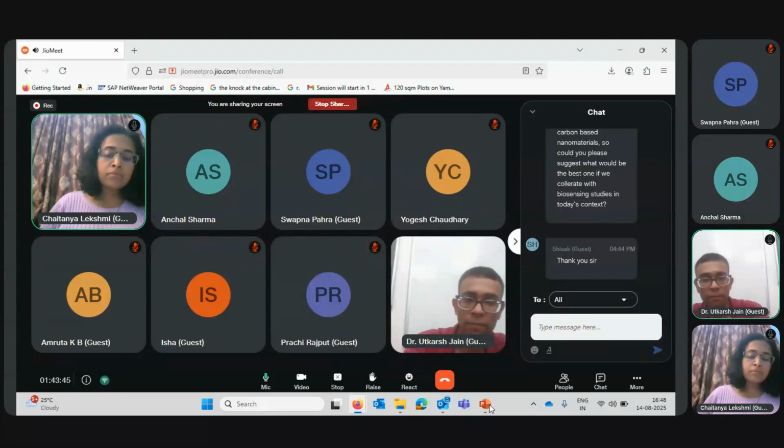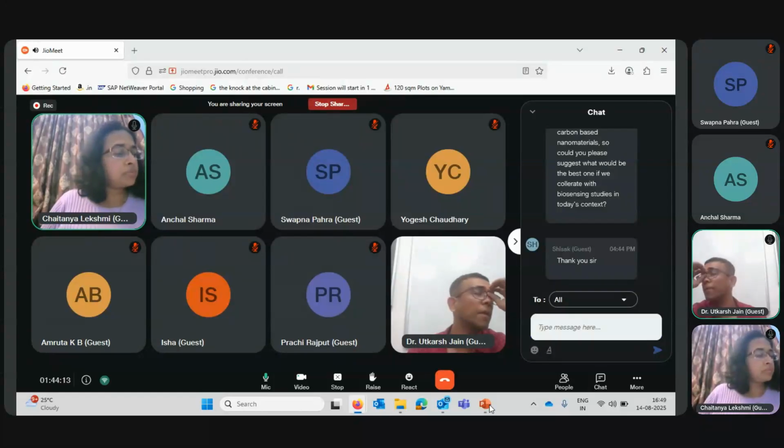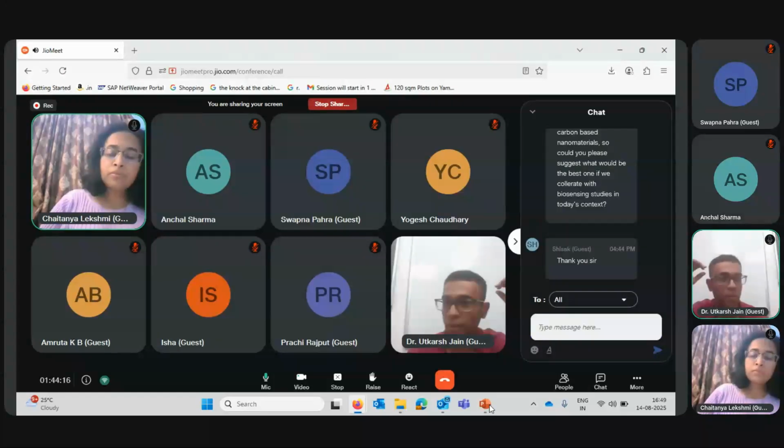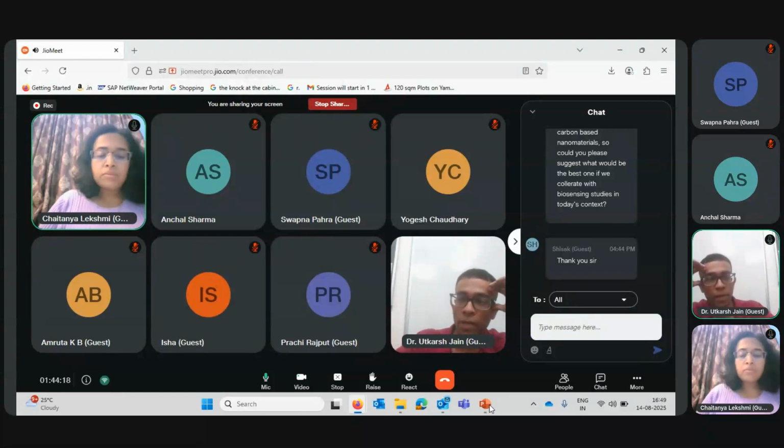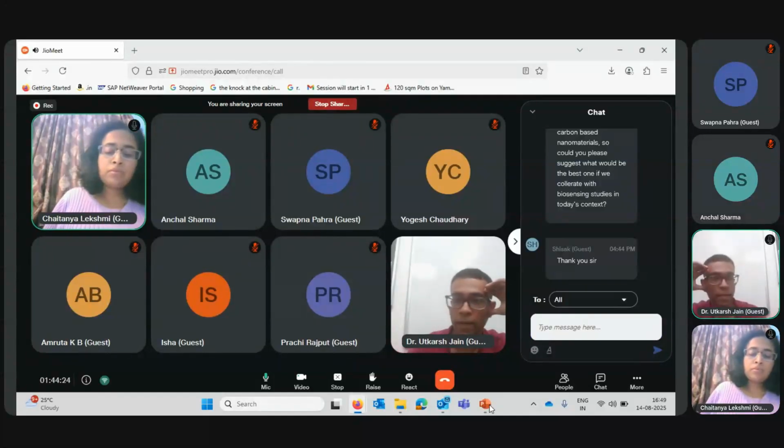So we then checked before nanomaterials coating and after nanomaterials coating. That's why we amplified the impedance response and got a broader range of signal through the EIS study as compared to the resistance. We have never tried resistance and other approaches, mainly EIS impedance-based approaches. So wherever we are checking the impedance caused on the electrode surface with biorecognition element binding to the surface, EIS is a really effective approach.